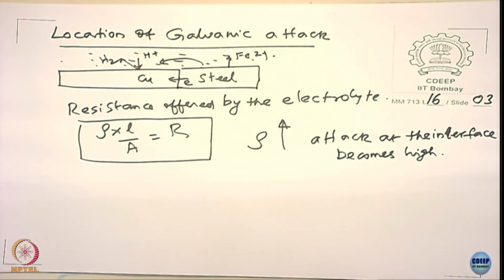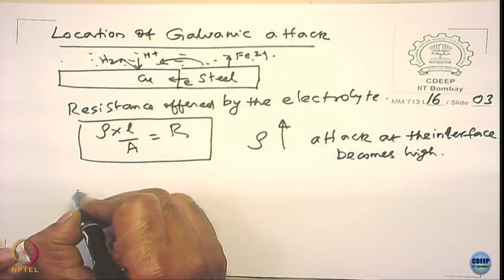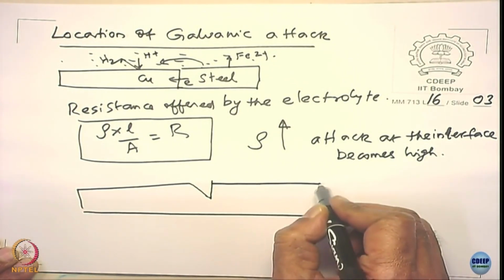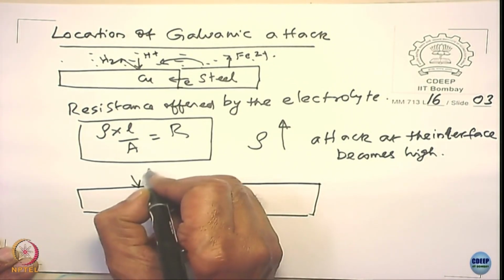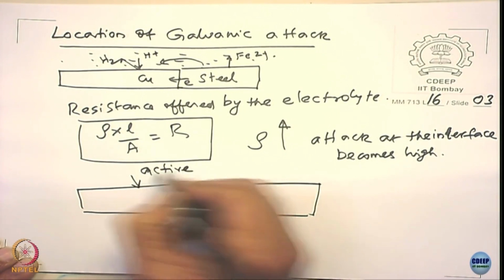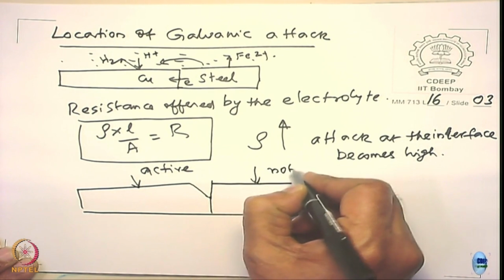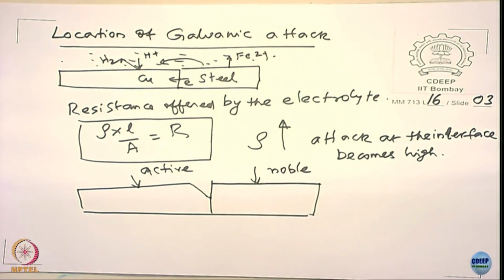In fact, this is one of the characteristics of galvanic corrosion. If you want to diagnose a problem, if you see in the industry that there are two different metals which are electrically shorted, and you want to show that there is galvanic corrosion, the first criterion is that the interface should have a deeper attack. In fact, the attack will be something like that. This is your active metal, your relatively noble metal.